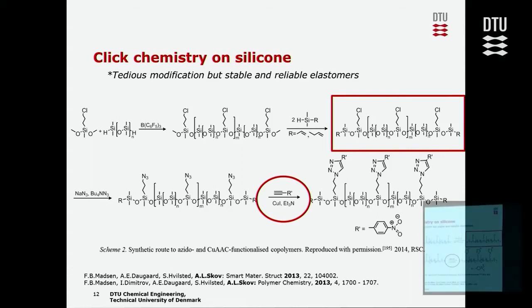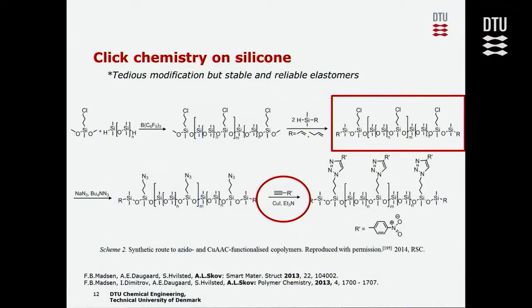Of course, it's a bit tedious. We go through a lot of steps in order to make the azido-functional siloxane. But on the other hand, then we are sure when we have made the polymers that we don't have any large-scale phase separation. Of course, these groups can agglomerate, and that's also what we saw, because for this type of elastomers, we realized that very small concentrations were very favorable, but when we went higher, we didn't actually get any improvement of our properties. And that we actually explained by simply having the phase separation on a nanoscopic level.